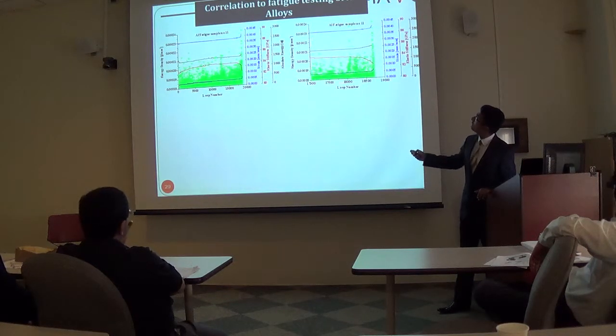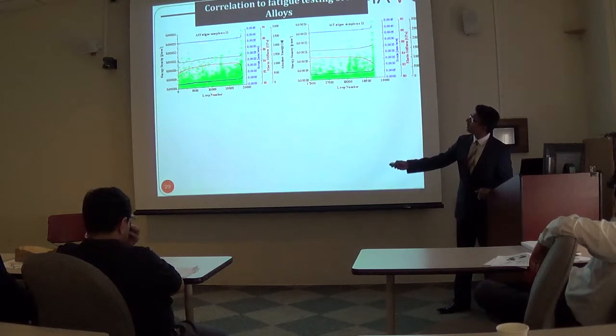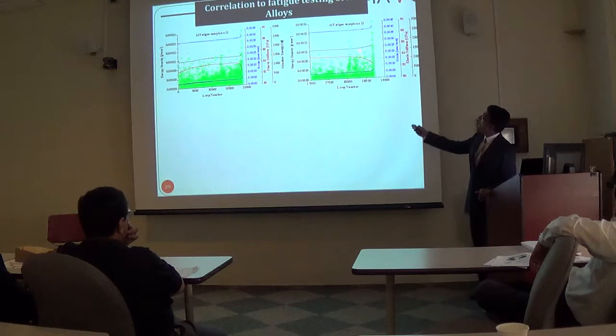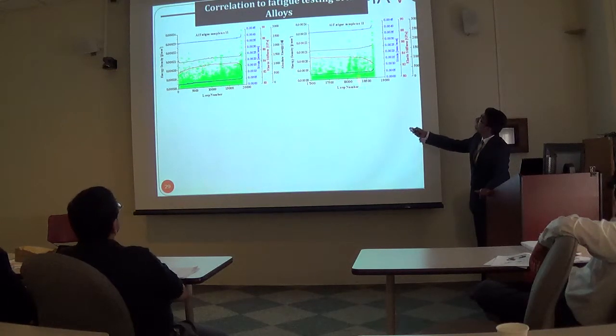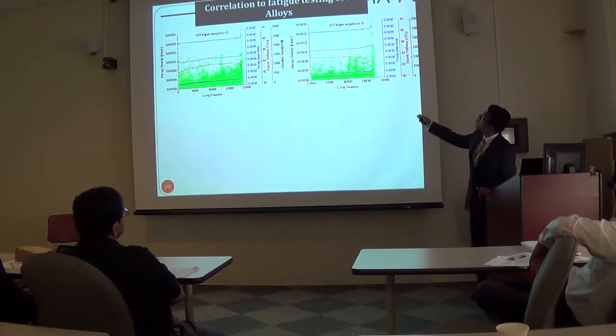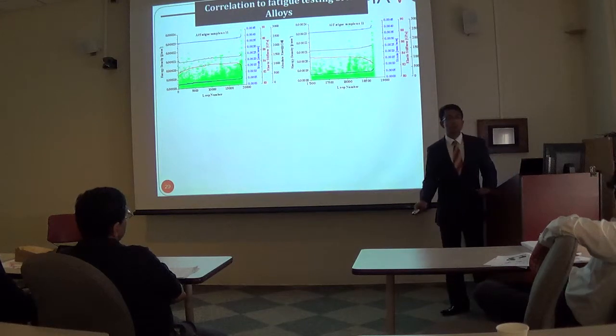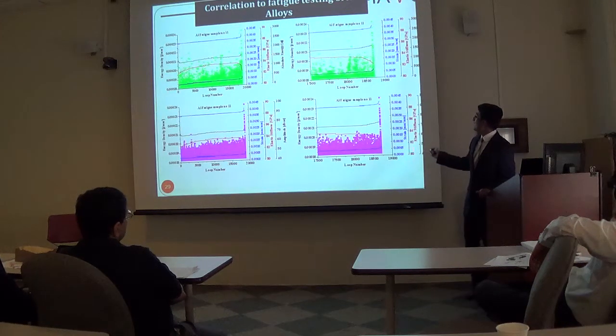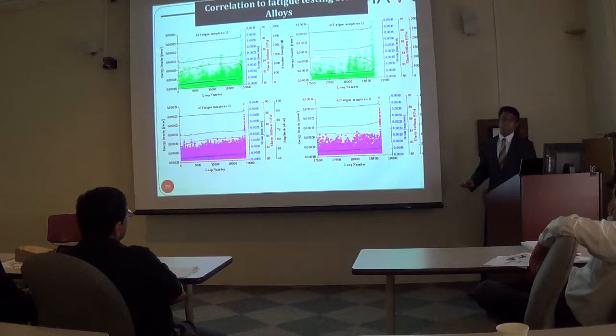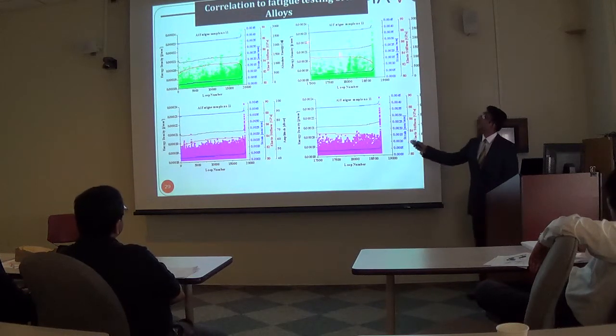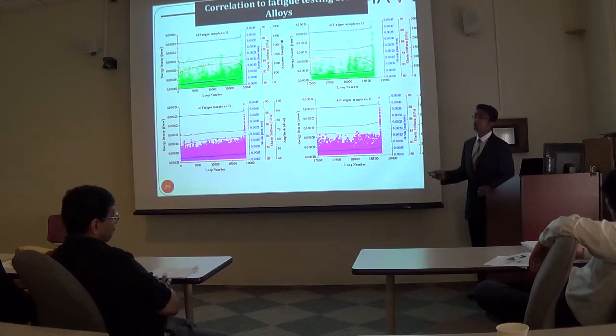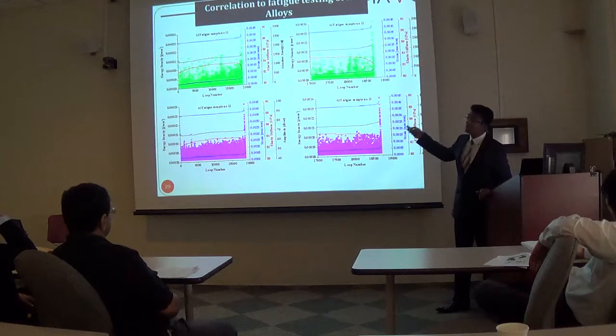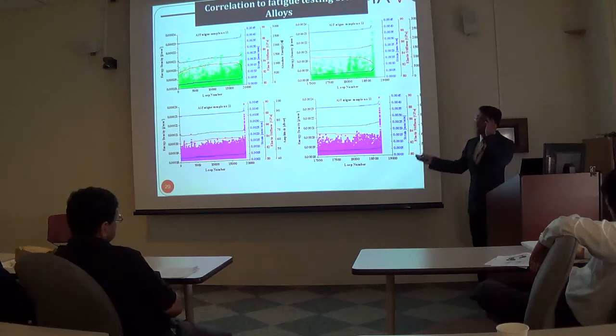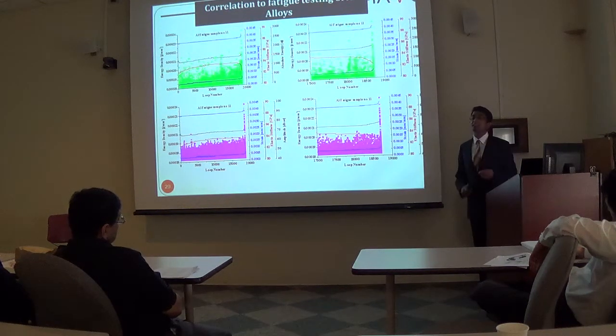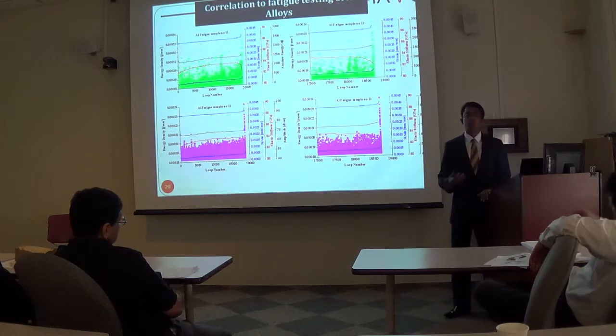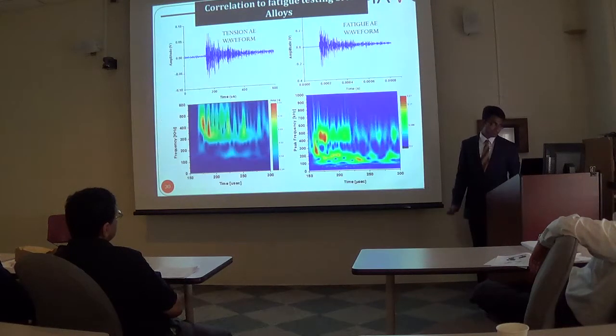And this graph here actually shows the zoomed in version of the last few stages, as you can note here. Right as you see that the stiffness changes and the strain changes, you can see the release of high absolute energy signals as well as high AE amplitude signals. But what was more interesting to see is how there was an early indication of absolute energy much prior to the strains and the stiffness picking it up. And thus, acoustic emission provides an early indication of the fatigue damage in the material.